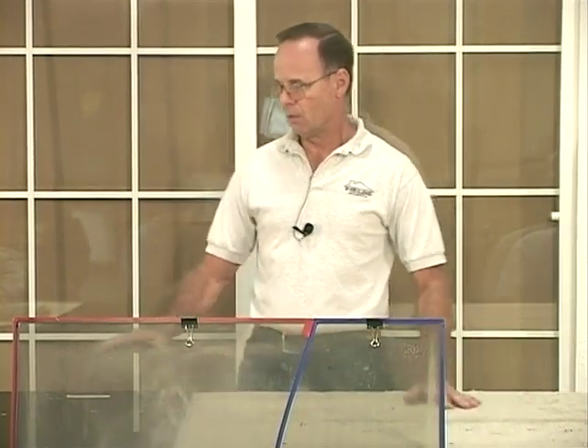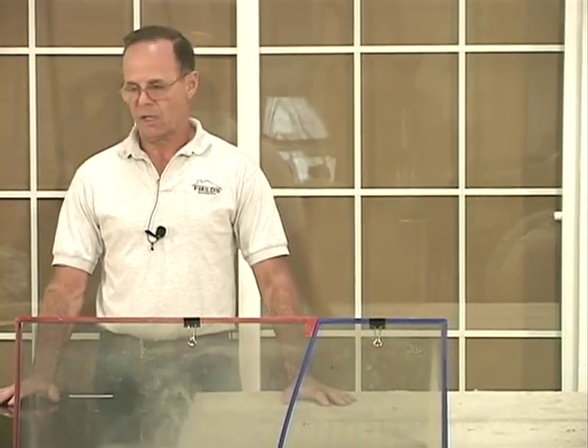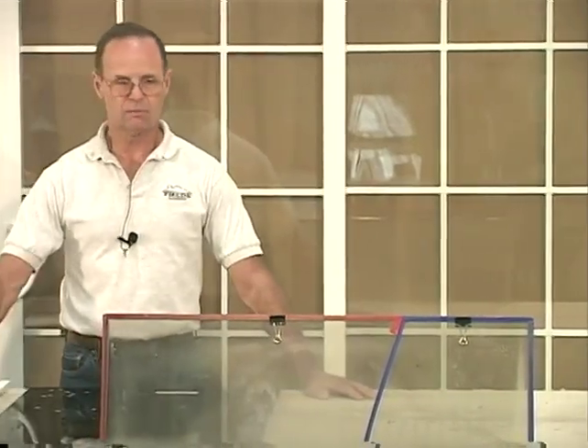And beyond that, you need to check your glass to be able to identify what side are we working with. So I suggest you get a UV lamp, preferably battery operated, so you don't have to carry around a plug, and shine it on the glass. And if it has a grayish reflection, you know that's the tin side. So that pretty well takes you out of the possibility of using HF, unless you want to take a chance of getting tin haze. If you have a clear reflection, then you can go ahead and use it and feel pretty confident you can be able to take the silicate deposits out and not have the tin haze problem.